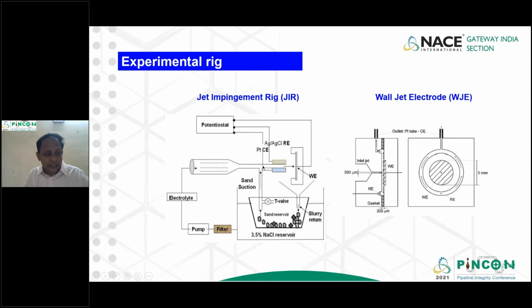But this is very tricky actually. This is the part we need to understand, how this experiment is being carried out. The sand and liquid get mixed here, and they go and hit your surface, which is called the working electrode. Similarly, in the other case, when erosion and corrosion are both there, I will conduct a similar experiment. But the moment I do erosion, I only put a cathodic protection of minus 200 millivolt extra on the surface, so that way I am able to control it, because I have a reference electrode on this side and a counter electrode here. This is the way I was carrying out the experiment.